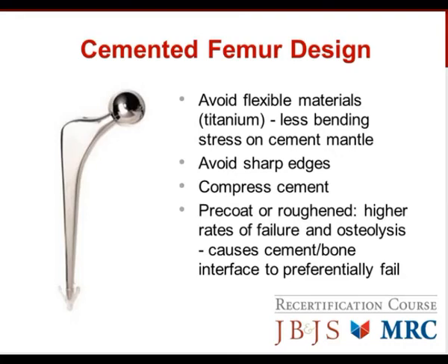Pre-coated and roughened cemented stems have not performed as well due to the preferential failure rate of the cement and bone interface. These roughened and pre-coated stems bond almost too strongly to the cement mantle.